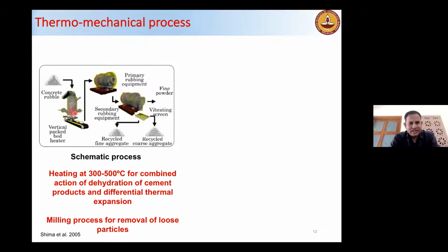Other one is the combined action of thermal and mechanical process. So first the crushed aggregates are heated. The temperature could be from 300 to 500 degrees C, and then with the combined action of heating and mechanical process. So basically heat will dehydrate the cement products, and also additionally there is differential thermal expansion at the interface of aggregate and mortar. And further milling process is used to remove the loose particles or the loose attached mortar. And there is a commercial portable plant in Japan where they've used 300 degrees C, and then two stages of milling processes, different for coarse and fines, and they could produce very high quality recycled aggregates. The capacity of this plant is 5 ton per hour.